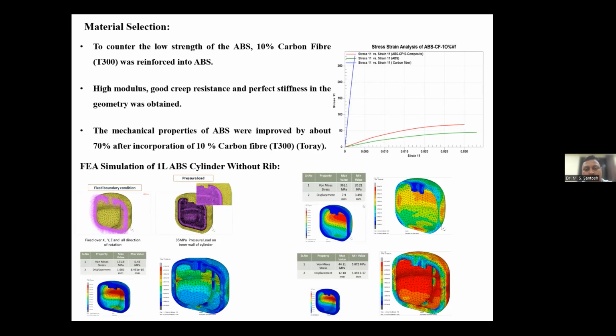While carrying out these studies, as I mentioned, by the introduction of 10% carbon fiber to ABS, the efficiency of the ABS material increased by about 70%, which is a significant number. And with the 70% increase in strength of the material, this qualified it to be used as a liner material.